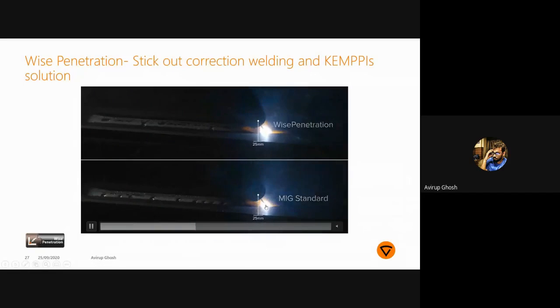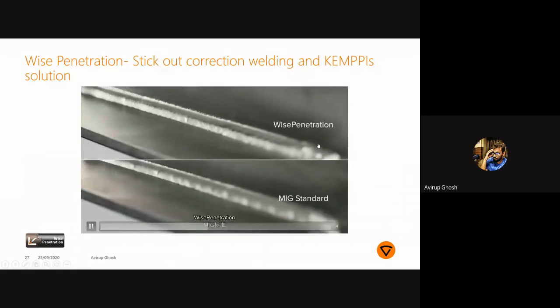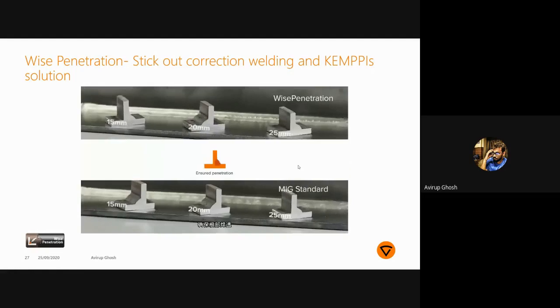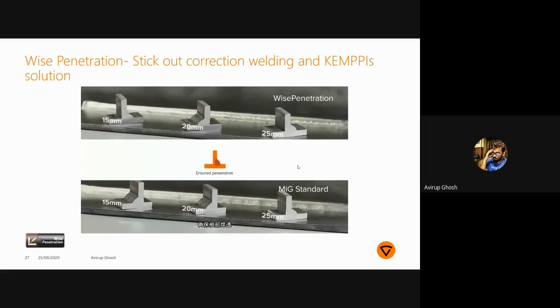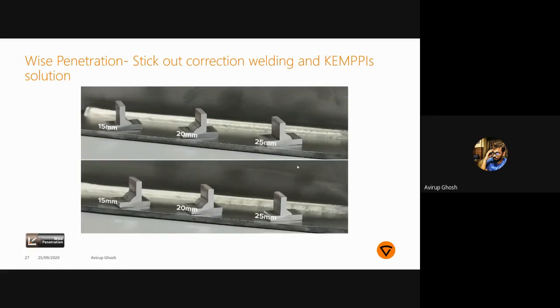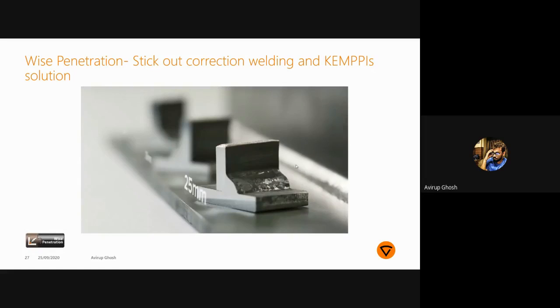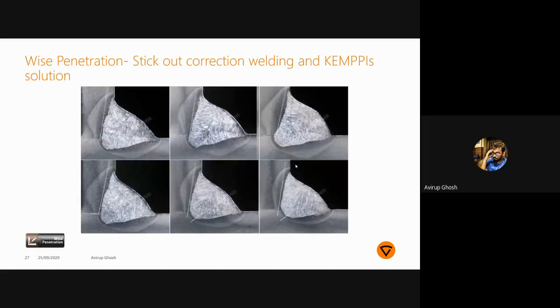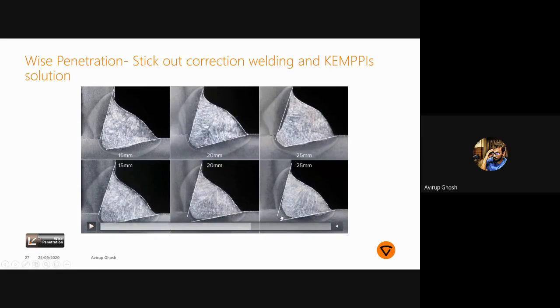This is a standard MIG. This is with WisePenetration. Bead wise, you will not feel there is much difference, but when you cut and check inside, we will see the difference. It will be shown here. Yeah, if I pause here, you will come to understand. See what happens when there is a 15 mm stick out, when there is a 20 mm stick out, and when there is a 25 mm stick out. You can clearly see the penetration level has gone down. The penetration is lesser here.